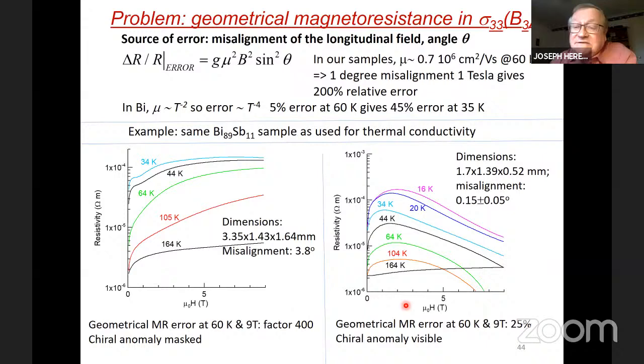Now, let's take a little look more into the geometry we have. We really don't have the field perpendicular to the plane. We have the field parallel to the current, but we have a small misalignment angle theta. So then I can use that previous approximate formula to calculate my error bar on my resistivity measurement. And that would be the geometrical factor times mu squared B squared sine squared theta. So now a sample at 700,000 mobility at 60 Kelvin, give it 1 degree of misalignment, make it square. How much is the error? Well, 200%.